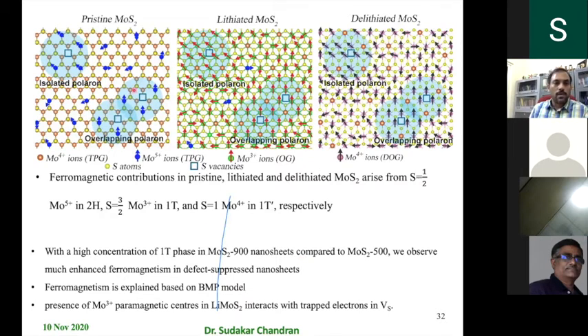So this is the pristine case where the magnetism mainly arises from the Mo5+ defect sites in association with the sulfur defects that would exist. So these form the polarons, overlapping polarons have all the spins oriented. Whereas in the lithiated case, the moly themselves become 3 unpaired electrons, they contribute. So S is equal to 3/2 from the Mo3+ state. And therefore the defect states present, they also pull all these, the interaction, and therefore they make it ferromagnetic.